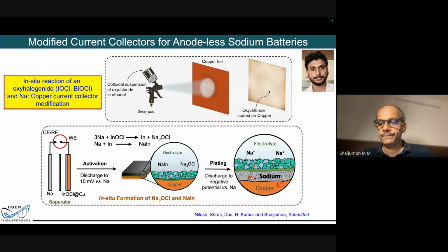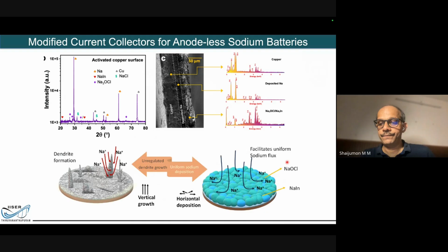And this is what I said a bit earlier: you form this layer, and then any sodium or lithium which is coming nicely goes through this material film, and it gets deposited onto the copper. And the sodium or lithium is very well protected by this layer which is coated, right? That basically gets sandwiched in between the copper and this modifier film. That's our approach, and that has resulted in very good, interesting studies.